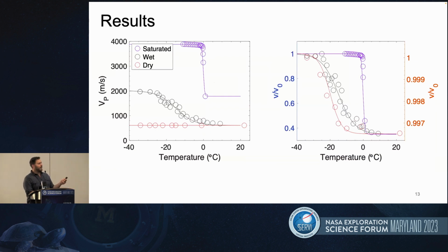So you can see that the blue data is a saturated sample. This is working with a lunar regolith analog material. And you can see most of the action happens right around zero. You go from an unfrozen, relatively slow velocity to a frozen, relatively high velocity. If you look at the wet sample, this is the one that's equilibrated with atmospheric water, 30% relative humidity, you get this interesting behavior that is similar to what you see for freezing in microporous soils, which is a freezing point depression effect.